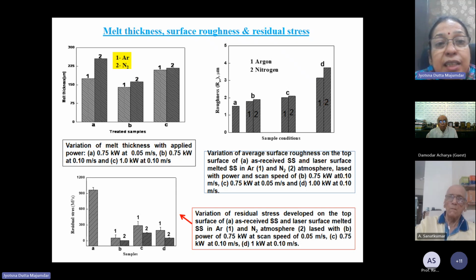So it's a very easy technique. You are simply melting it, and in one case you are melting in argon. When you use argon, naturally there is refinement of microstructure, and the rate of refinement depends on the argon flow rate as well. As you go on increasing the flow rate, your convection-dominated heat flow also increases, so cooling rate increases, as a result of which the degree of refinement also increases. But when you use nitrogen as environment, there you introduce a lot of nitrides in the structure. Depending on the material, we saw in titanium, 316L stainless steel, mild steel, everywhere we found very fine nitrides.